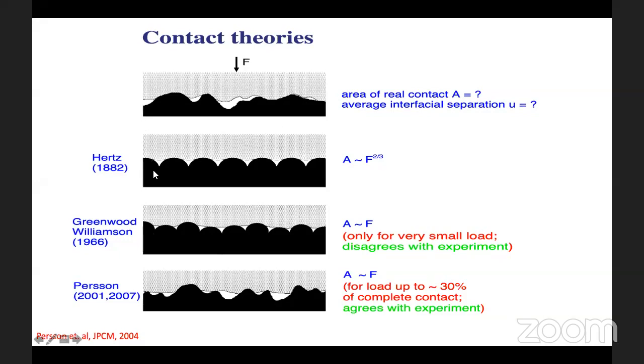So Hertz, in 1882, took an elastic solid and compressed it against a rigid solid having spherical bumps of equal radius. Each contact here can be treated as an individual Hertz contact, like this. And then you can come to a conclusion from these calculations that the area of real contact depends non-linearly on the applied normal force.